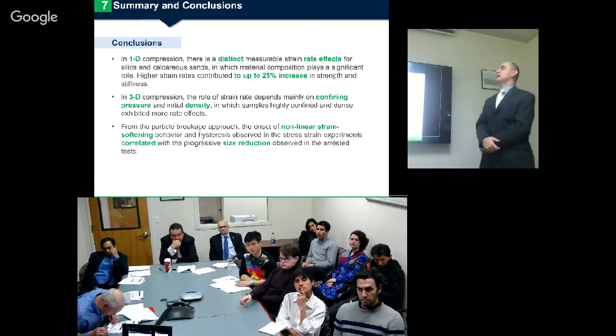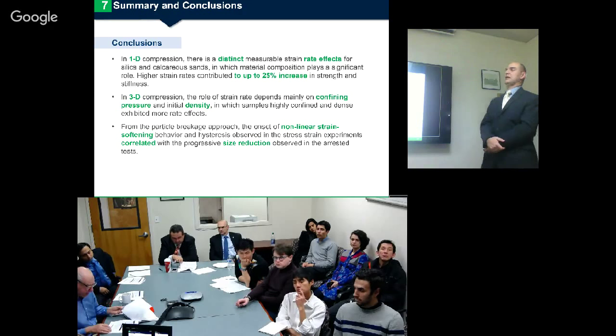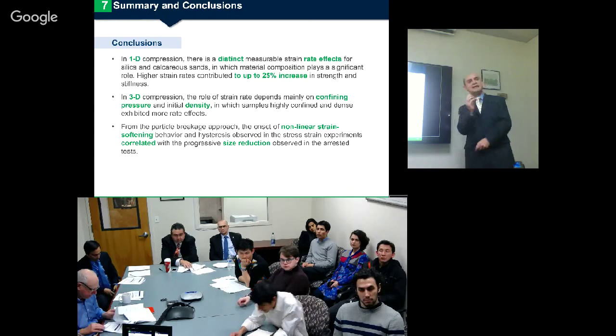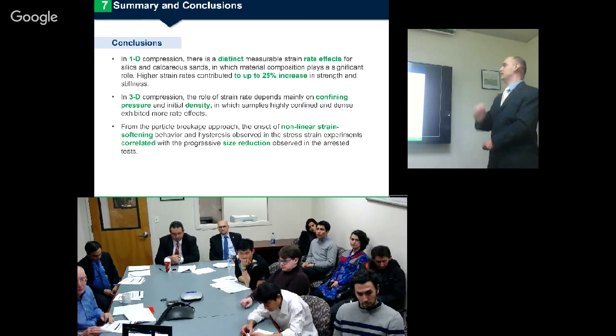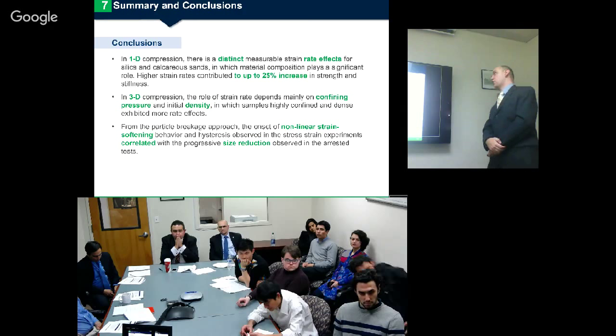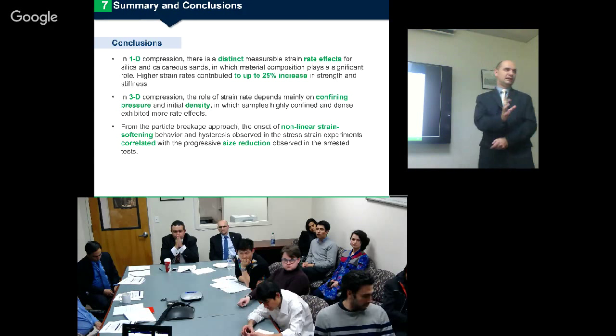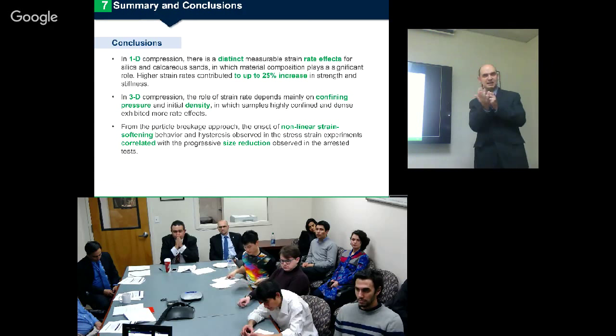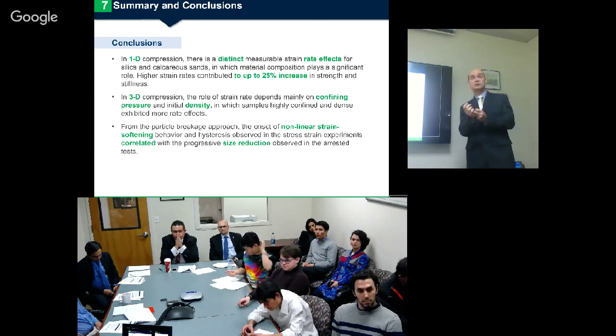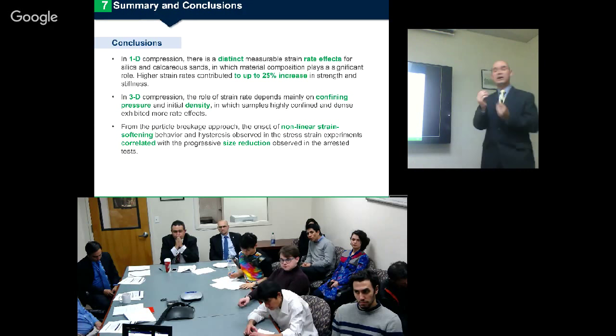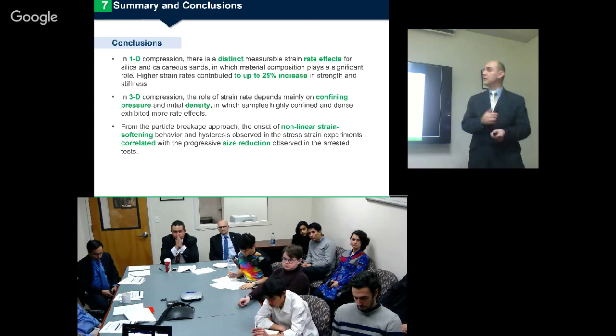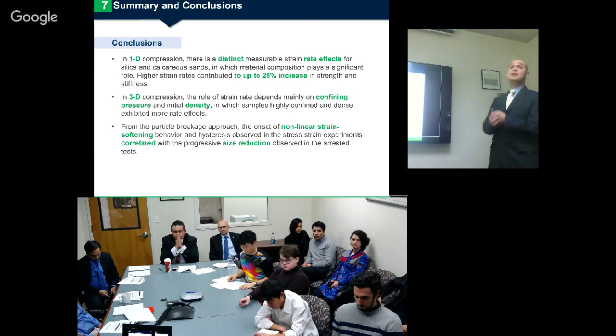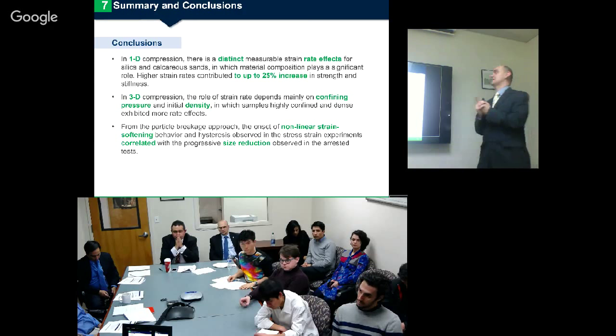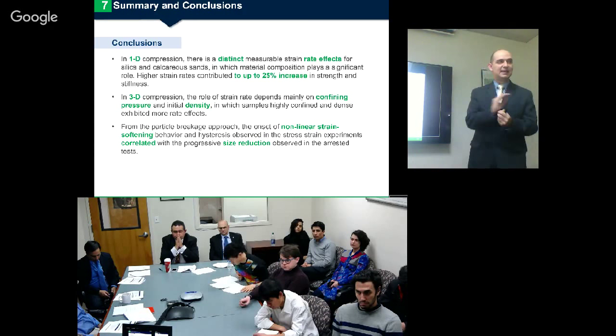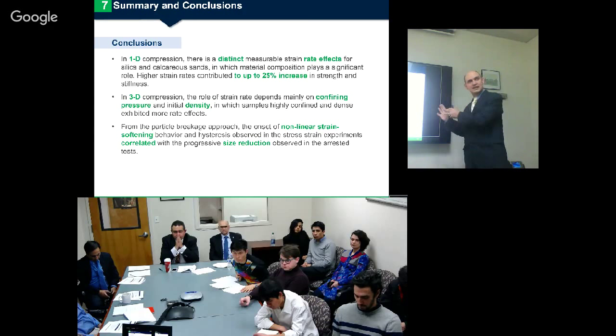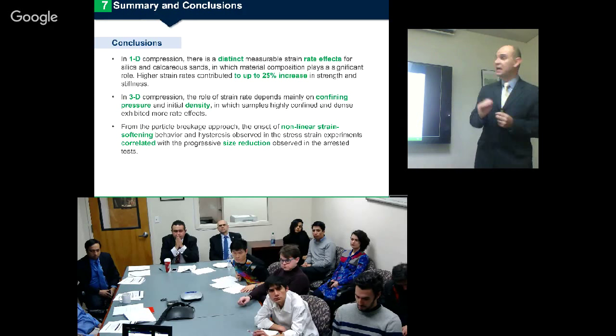And the conclusions that I found: in uniaxial compression conditions, there is a distinct measurable strain rate effect for silica sand and coral sand. However, the material, which is not fully investigated in detail, plays a significant role. That increase could be up to 25% in strength and stiffness. In triaxial compression, the role of the strain rate depends mainly, at least from this study, on confining stresses and the density of the material.